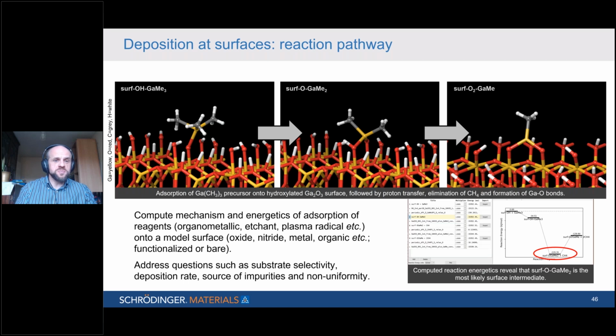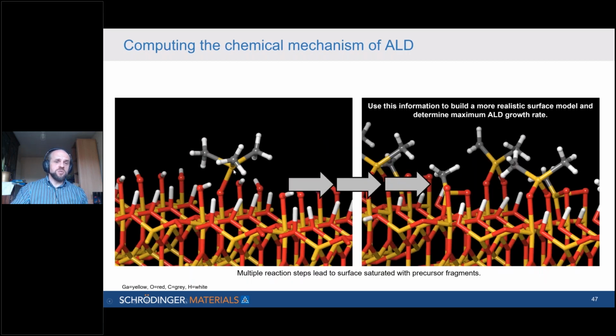But you can imagine how we can change the substrate and look at substrate selectivity. We can change the precursors coming in, the effect of ligands, whether ligands decompose and form impurities, and whether different functional groups on the surface interact with one another and what effect that has. So we can really address a lot of the important process questions with these types of quantum mechanical calculations. And going from the simple picture I've just shown you, we can start to build up surface models that really look like what is happening on the surface during the growth process, with different species affecting one another, causing the surface to be covered and saturated. And that's crucial; certainly for atomic layer deposition, saturation is the crucial thing that drives the process. We can then work out the growth rate and link that back to experiment.